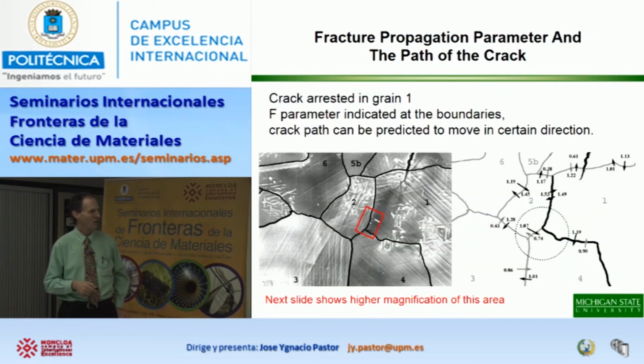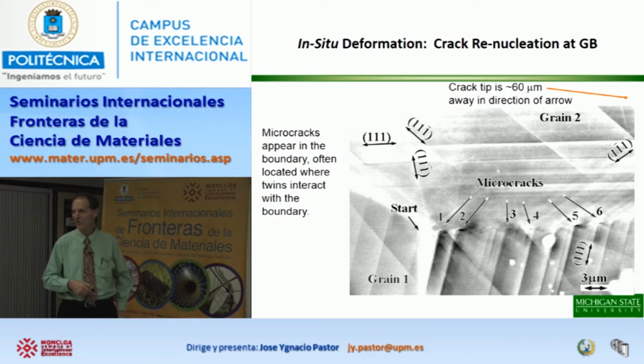So thus, we could map out all the grain boundaries in the neighborhood of where the crack has not yet gone and see if we could figure out where the weak areas in the microstructure were. Well, this area is interesting because I mentioned to you that this crack was arrested, and there's all these twins going this way. I'm going to zoom in on this one next time. So if you tilt your head to the left and then bring it straight up again, you'll see this same area right there. So I've rotated that image. And one sees that along this boundary, there's six different little microcracks associated with these twins. So this region looks like it's about ready to open up into a bigger crack if more of this twinning takes place.